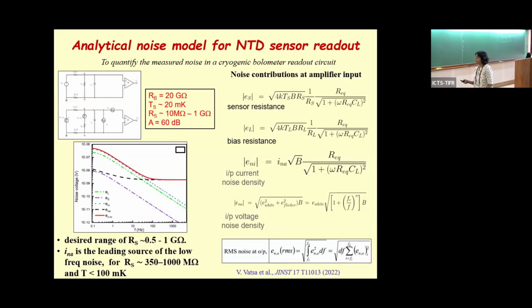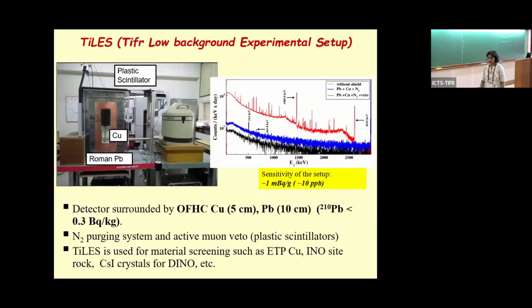An analytical noise model was developed. You see the contributions to the noise: because you have a sensor resistance at a gigaohm, you have Johnson noise from the resistors. Then you have the amplifier current noise density and the voltage noise density, white noise. What we showed was that the most dominant source, in our range of interest below 100 millikelvin, is actually the current noise density of the amplifier, and the resistance of the sensor should remain below 1 gigaohm if we don't want the Johnson noise to become a dominant factor.